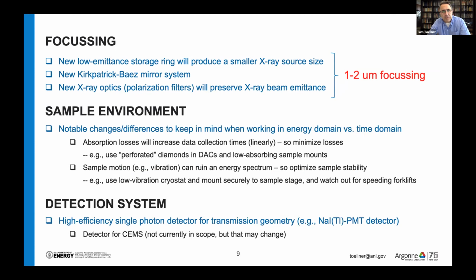The sample environment, I just wanted to make a note of some changes in terms of what one needs to pay attention to. The absorption losses around the sample environment are quite critical, and any of those should be minimized to a great extent. That wasn't an issue in the time domain because we were already using an absorber, and one could simply remove some absorber to compensate for any additional losses around the sample. That's not the case in the energy domain.